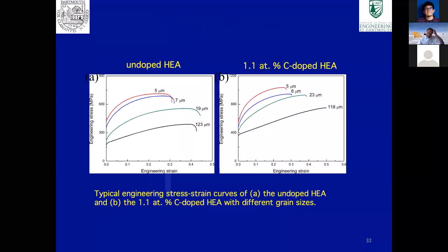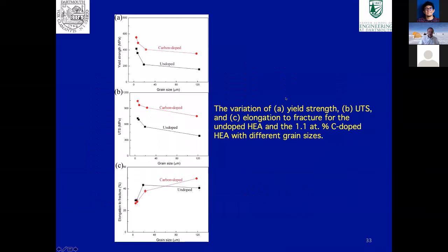So we looked at the mechanical properties of the recrystallized material, and the ones that we recrystallized at different temperatures had different grain sizes. So this is the undoped high-entropy alloy, and this is the carbon-doped. And you can see as you decrease the grain size in both cases, the yield strength increases, and so does the ultimate tensile strength, but the ductility decreases in both cases, as you might expect.